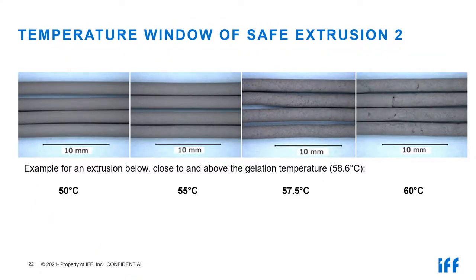This is another very nice example demonstrating how important it is to stay at a large distance in this safe window of operation. In a test batch, we measured with our torque rheometer that the gelation temperature of the cellulose ether in a certain mix was 58.6 centigrade. Then we made 4 extrusion tests at 4 different temperatures and checked the profile quality. Please have a look at the first picture. We extruded this material at 50 centigrade, so nearly 10 degrees below the gelation temperature.